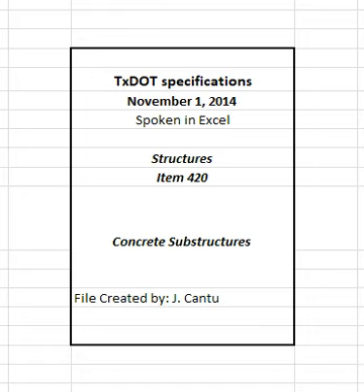Remove forms for vertical surfaces after the concrete has aged a minimum of 12 hours after initial set, provided the removal can be done without damage to the concrete unless otherwise directed. Keep forms for mass placements in place for 4 days following concrete placement unless otherwise approved based on the outcome of the heat control plan outlined in section 420.4.7.14, mass placements. Leave in place weight supporting forms and falsework spanning more than 1 foot for all bridge components and culvert slabs except as directed otherwise until the concrete has attained a compressive strength of 2,500 psi. Remove forms for other structural components as necessary.